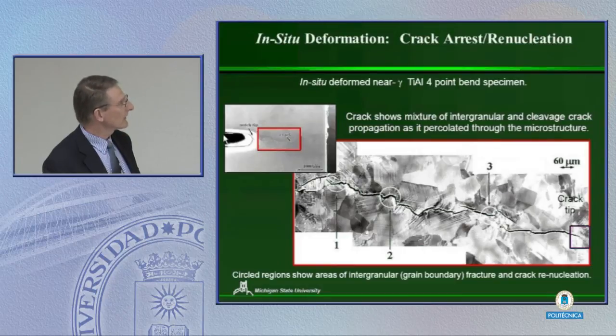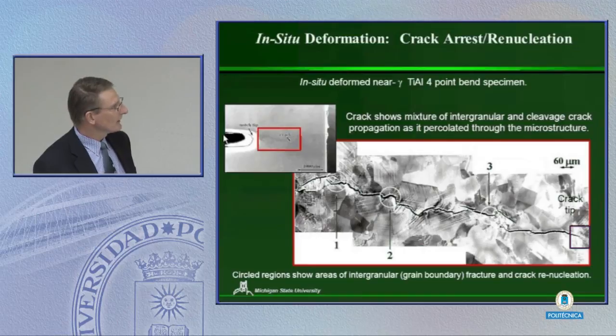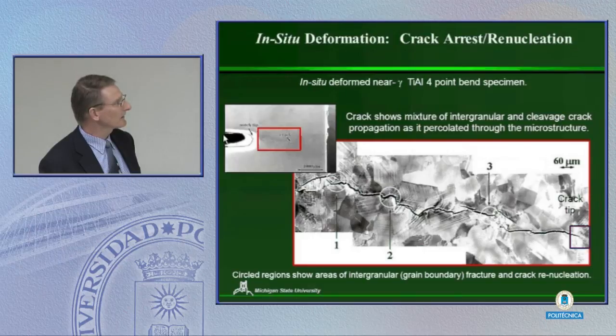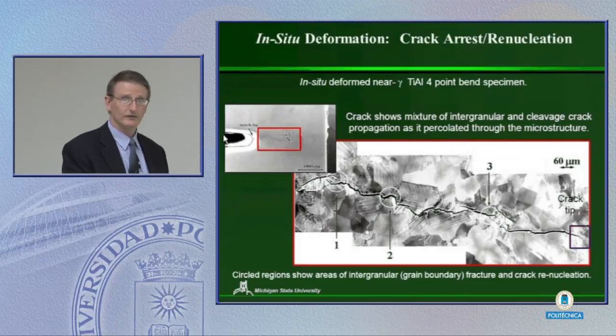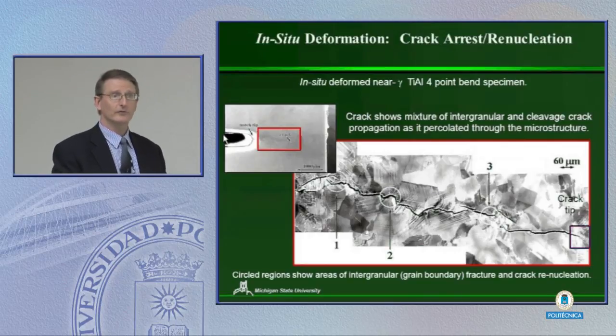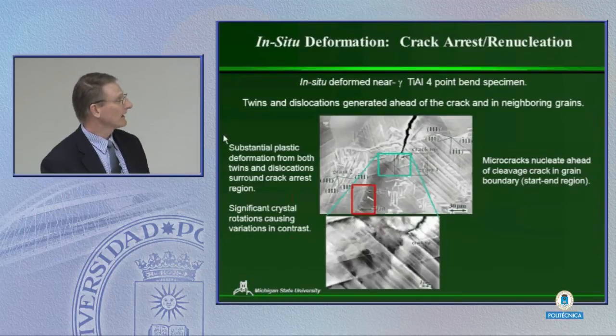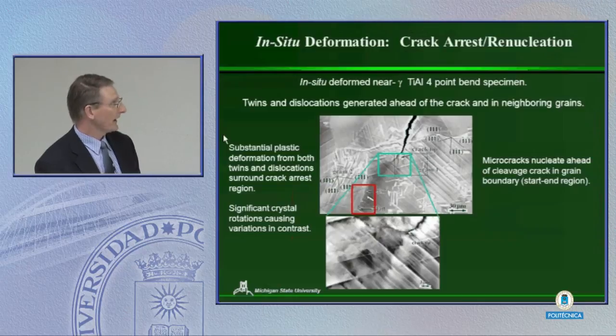If we look at a crack tip propagating out of one of these notches here, we can see some interesting things. As the crack propagates along, in general, it propagates by cleavage. But every now and then, we get some intergranular failure. And not only that, we see places like this where the crack propagated here and suddenly jumped onto a different plane. And we've seen that in a number of different places where we go from cleavage to intergranular. And sometimes intergranular is renucleating on a different plane. Or, I'm sorry, ahead of the crack.